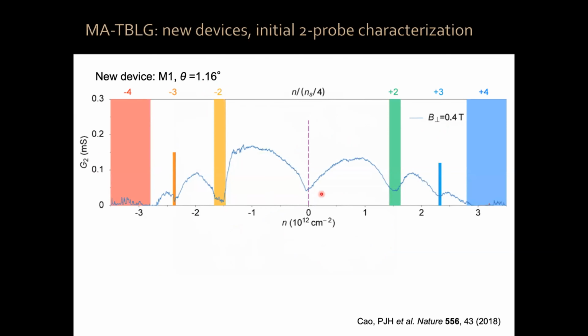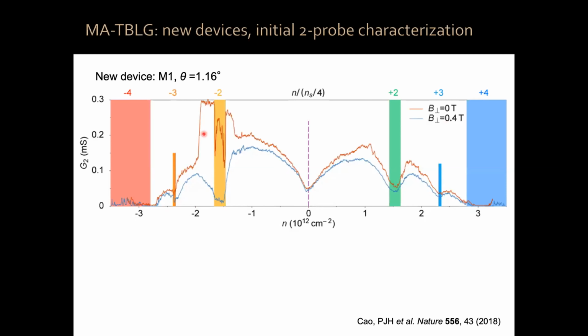So you see there is this V shape near charge neutrality. You have insulating states at 4 electrons and 4 holes per moiré unit cell. You also have dips in conductance at 2 electrons and 2 holes per moiré unit cell. Other stuff happens at 3 holes and 3 electrons. There's a lot more stuff going on here that I'm not telling you about. But the important thing is, if we now remove the magnetic field, you can see that not too much happened here, but here a lot of stuff happens.